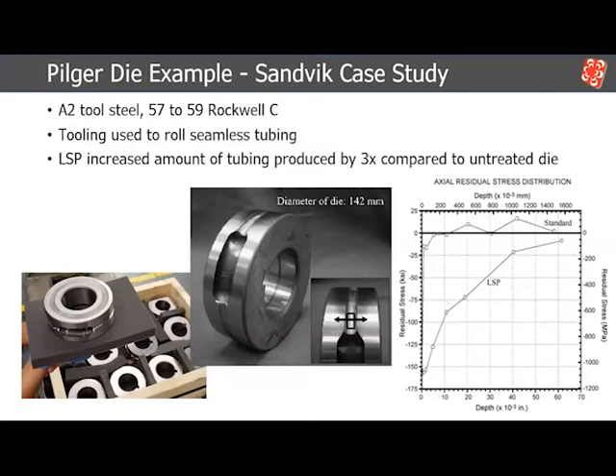On the same theme of fatigue life enhancement, a regular component that we laser peen is the Pilger dies. These Pilger dies are mainly experiencing mechanical stresses. A study with Sandvik has previously shown that laser peening was able to improve the life of these dies by around 3 times. Looking a bit deeper into this application, the majority of the failures and the highest location for stresses are in that groove where your crack initiates and propagates.